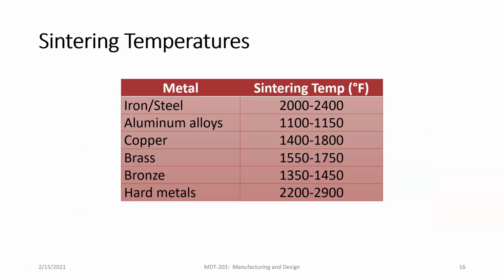Some ideas for the sintering temperatures. Obviously these are very loose. You need to look at the specific properties of the powder, the specific recipe of the powder that you're going to be using. But just to give you an idea, iron and steel in the neighborhood of the low 2000 degrees Fahrenheit, aluminum a little bit above 1000 degrees Fahrenheit, copper 1400 to 1800, brass a little bit higher, 1550 to 1750 degrees Fahrenheit, bronze in that same neighborhood.